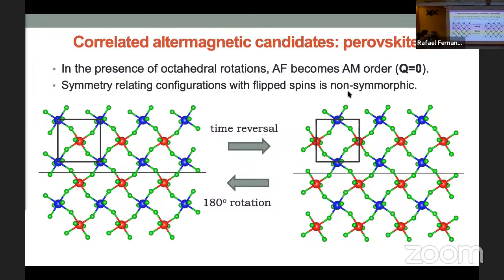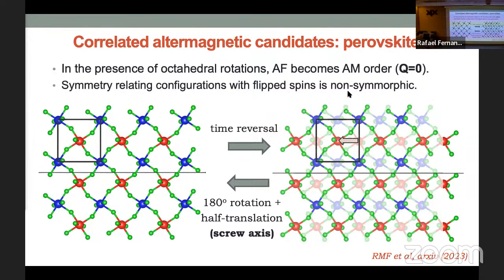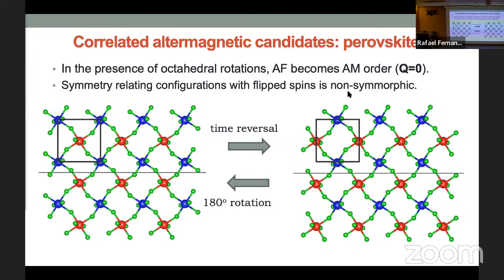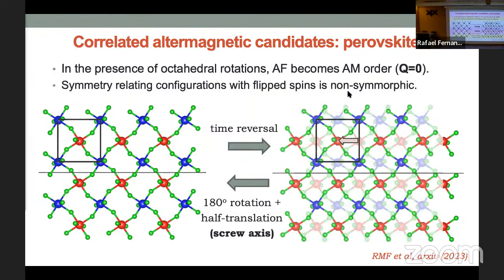All right, well, this is not enough, right? This clearly made my units not match, even though both have two atoms. But what I clearly can do is a half translation, right? If I do a half translation along the direction of the axis, so a screw, I actually get exactly where I started. And that's what I mentioned earlier, right? Usually, in several of these materials, the symmetries that make them equivalent involve some non-symmorphic operation. Okay? So here's the screw axis, and then you get exactly where you started. Okay, so this is just showing that these Pnma structures are intrinsically altermagnetic without spin orbit coupling.